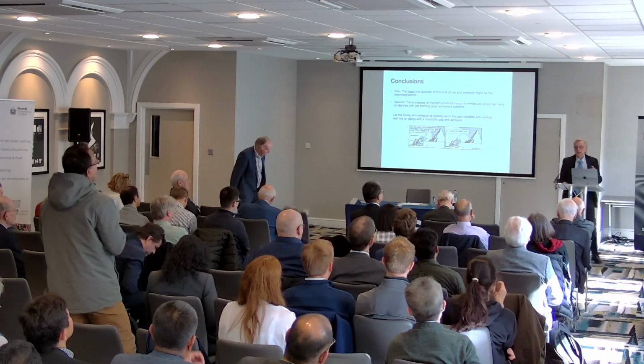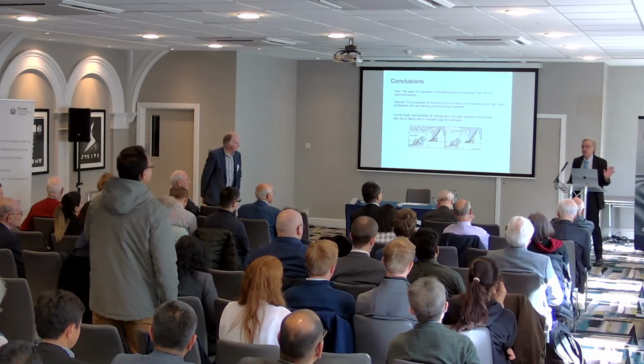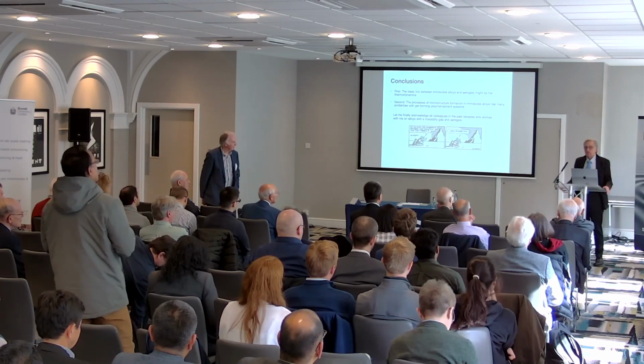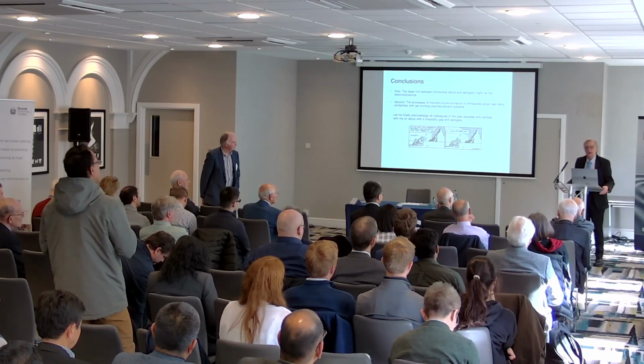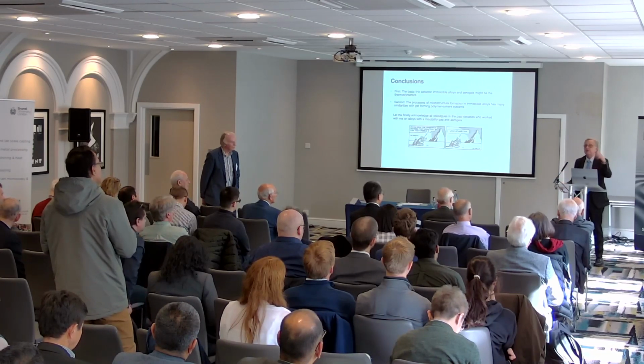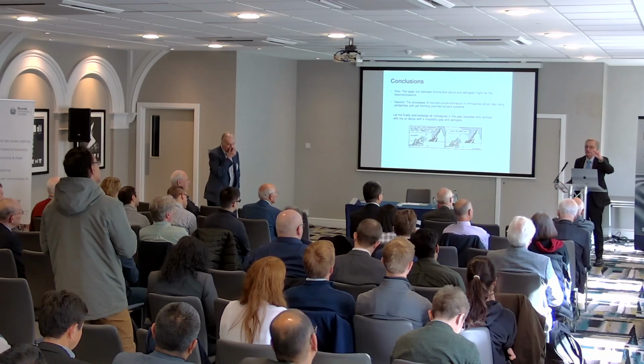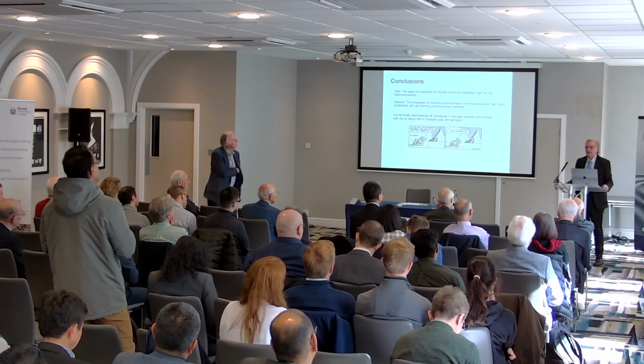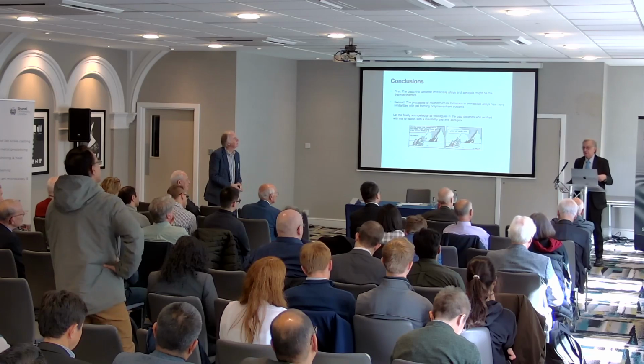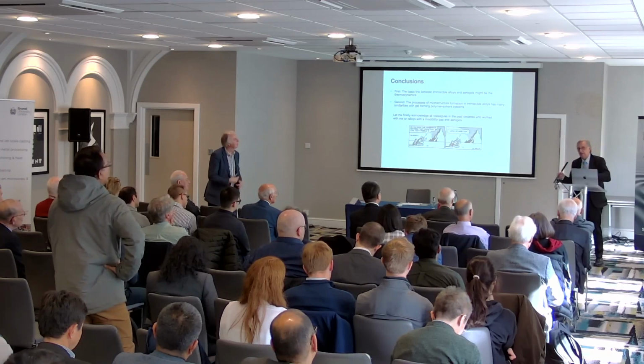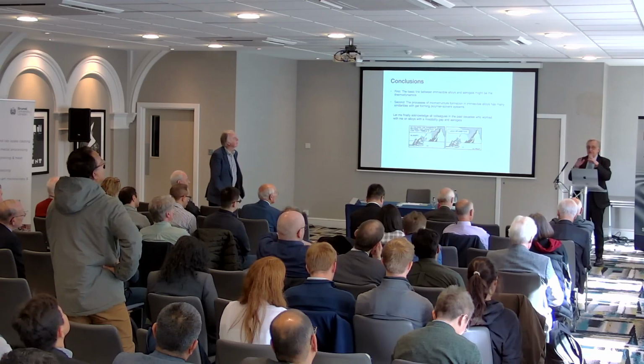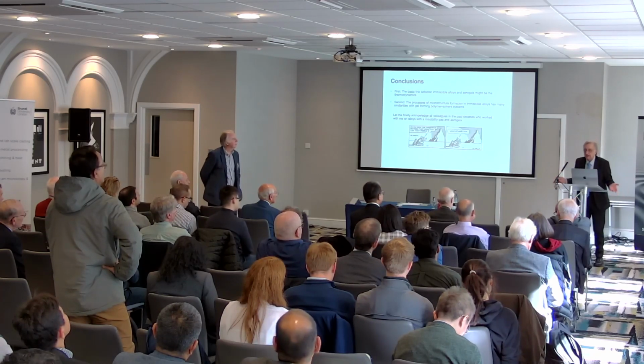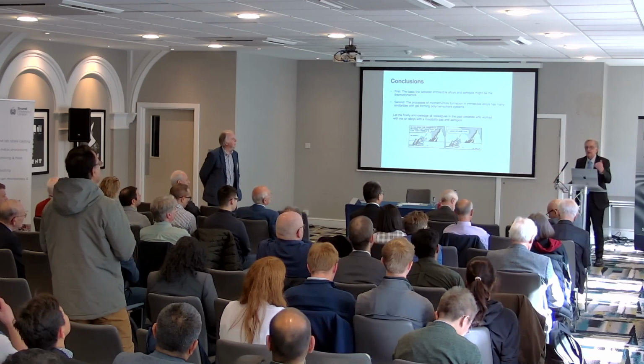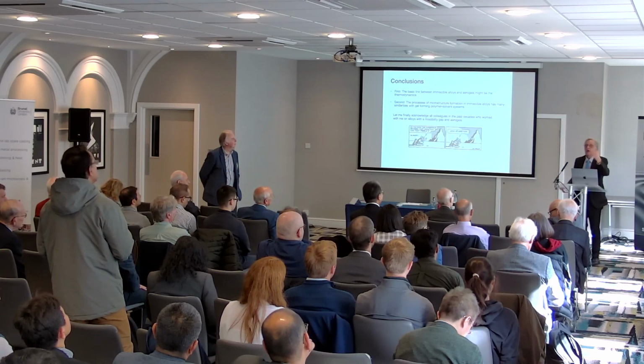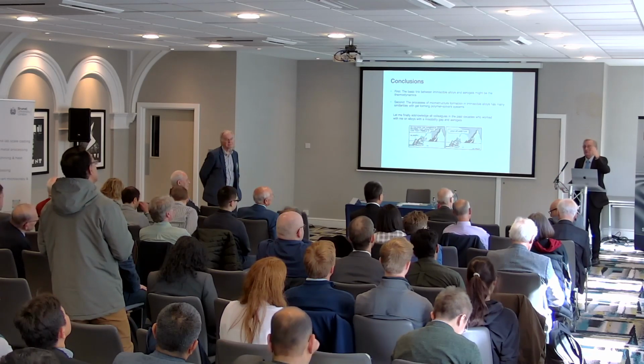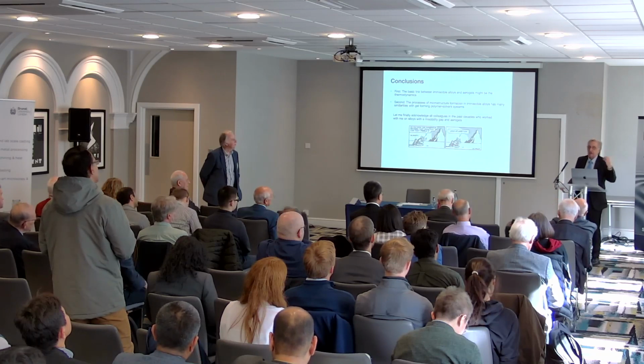First of all, for alloys, there's no way to suppress it. You can make, of course, rapid solidification. This was done. The only difference is then you get very tiny droplets. But the phase separation is always there. I do not know of any of the immiscible systems with liquid miscibility gap that you could maybe make an amorphous material. You just get something like 10 nanometers, which was done to study then the effect of curvature on nucleation undercooling.